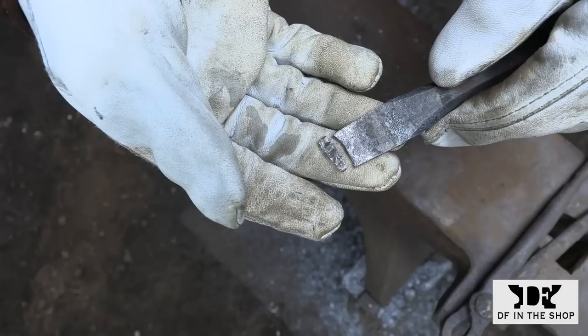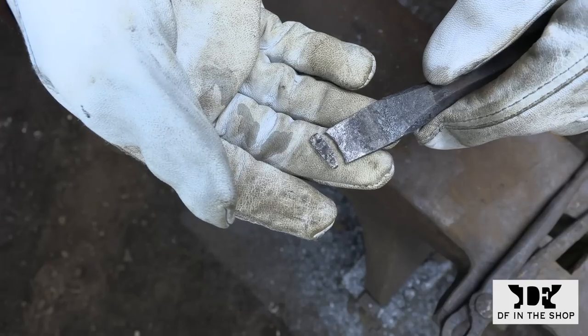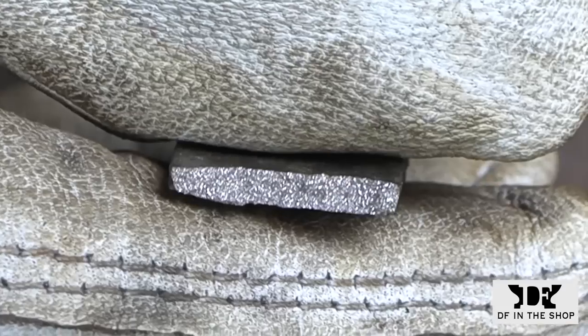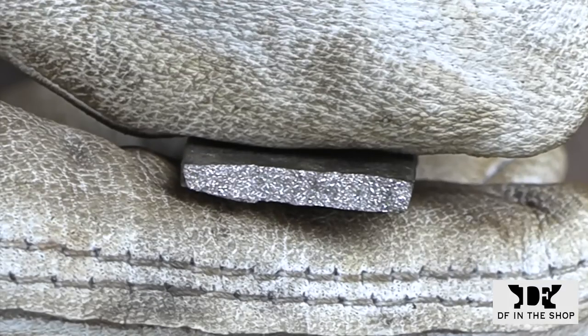So here's the piece right out of the quench. That jagged edge was a huge crack, and I basically broke it off just by snapping it with my fingers. So here's a look at the inside. You can see how coarse the grain structure is. So even if I had gotten this tool to work, if it hadn't cracked and I was able to temper it and put an edge on it, the first time I used this tool, it would have shattered, just because the internal structure just isn't there to support a cutting edge.